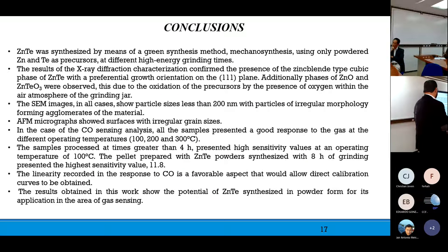As a conclusion, the zinc telluride was synthesized by means of a green synthesis method, mechanosynthesis, using only powdered zinc and tellurium as precursors at different high energy grinding times. The results of the X-ray diffraction characterization confirmed the presence of the zinc blende type cubic phase of the zinc telluride with a preferential growth orientation on the 111 plane. Additionally, phases corresponding to zinc oxide and zinc tellurite were observed.